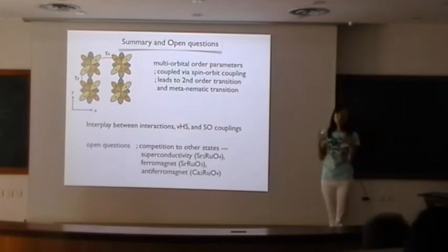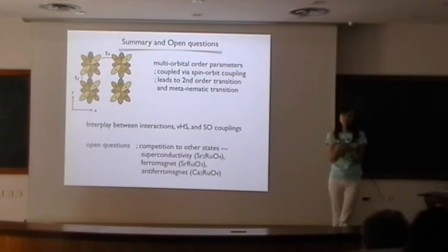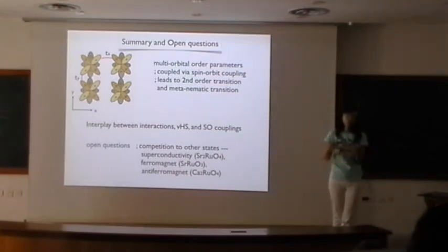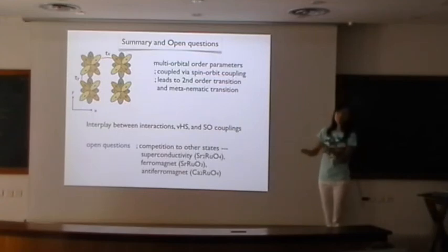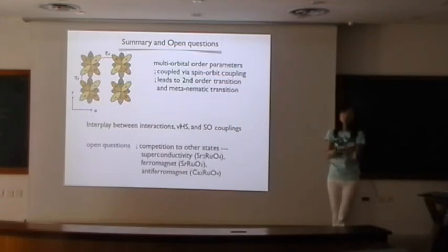If I put in everything you can think of, to be more realistic, what happens is that if you make the leading instability coming from orbital ordering, because it's coming from XZ, YZ, the Fermi surface is one lead. Once you have the nematic, the Fermi surface will become open, widely open. As a leading instability, that is a huge change in the Fermi surface topology. So that's why I put the orbital ordering as an induced ordering. But in principle, that's based on using guidance from the experimental data rather than theoretical selection.